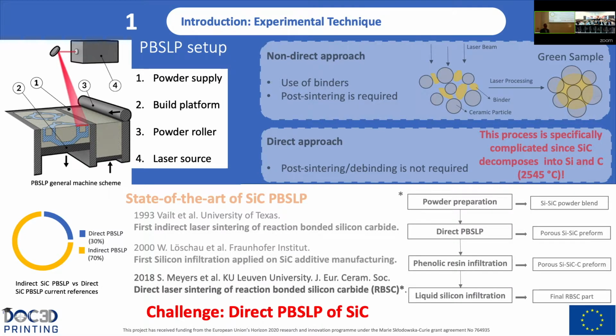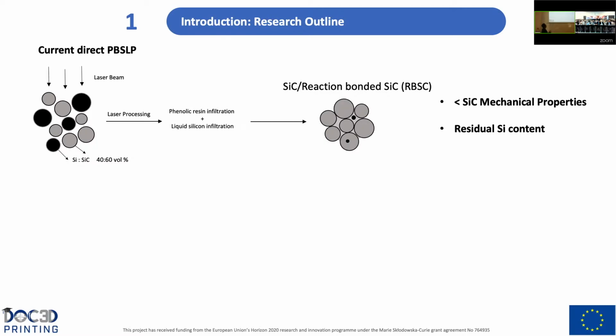So it's still a challenge to achieve direct powder bed selective laser processing of silicon carbide in the absence of additives or, as we have seen, other initial powders. So as we have seen, this is the latest strategy adopted by researchers and some industries. And since we are obtaining at the end a composite of silicon carbide and reaction-bonded silicon carbide, we have a negative impact compared to, let's say, pure silicon carbide. And at the end of the process, we also have some residual silicon content that, for example, for some chemical applications should be avoided.